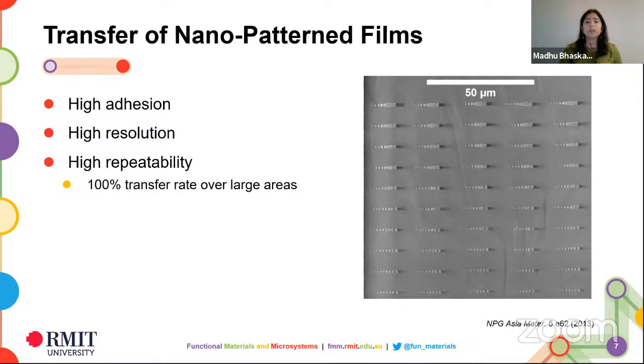It's a beautiful process because we can use it again and again. We can use it for nano patterned films and for micro patterned films. The adhesion is really good because the oxide is semi-embedded inside the polymer. You can get excellent resolution, as this image shows you, and you can do large areas. We've done up to 4-inch silicon wafers, and you can get a 100% transfer rate over a very large area.